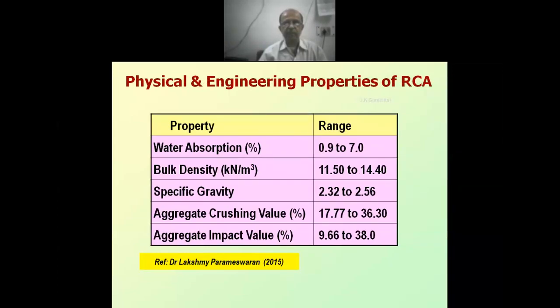Physical and engineering properties of RCA as reported by Dr. Lakshmi Parameswaran. Water absorption up to 7%. Bulk density around 11.5 to 14.4 kilonewton per meter cube. Specific gravity around 2.32 to 2.56. Aggregate crushing value about 18 to 36%. Aggregate impact value around 10% to 38%. So this shows how heterogeneous the material is.